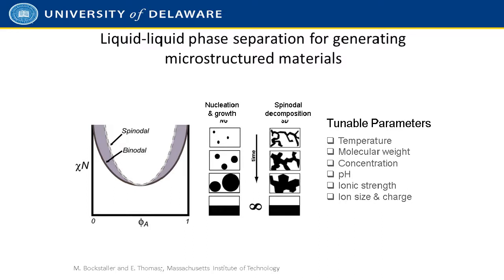Our particular approach to making these microstructured hydrogels takes advantage of the liquid-liquid phase separation that different polymers and proteins can undergo. What I show on the left is a simple rendering of the coexistence curve for a phase separation process in which a single phase is observed if you're below the parabolic shape. But once inside the envelope traced by the curve, phase separation happens. Phase separation can happen by two different mechanisms.